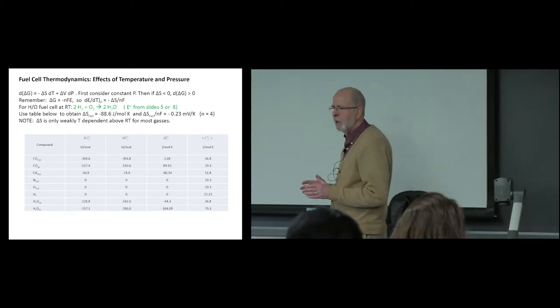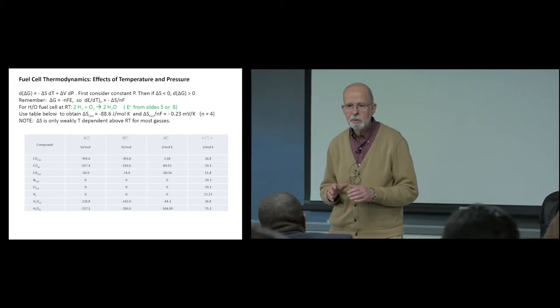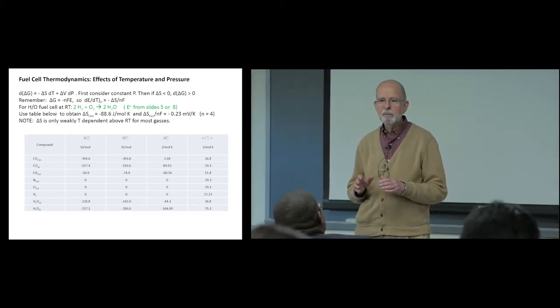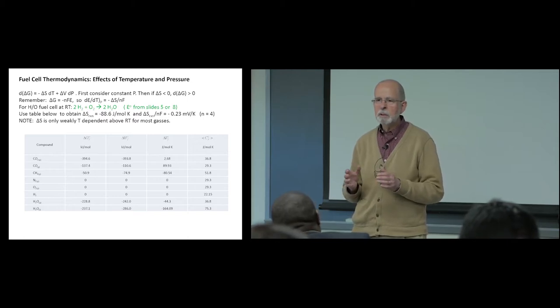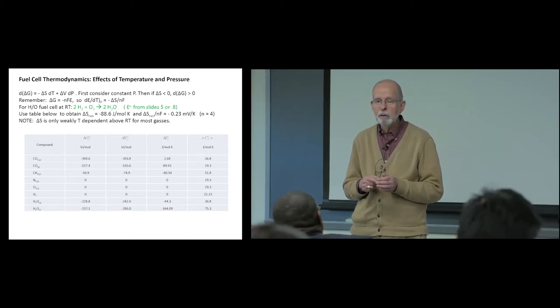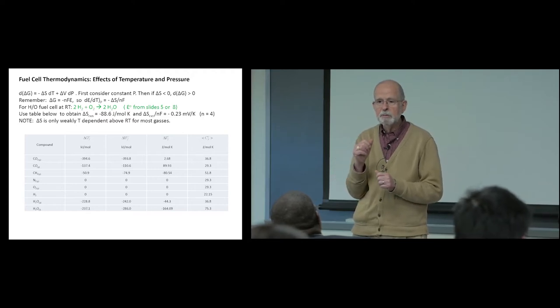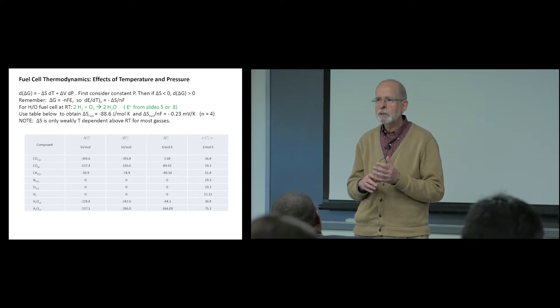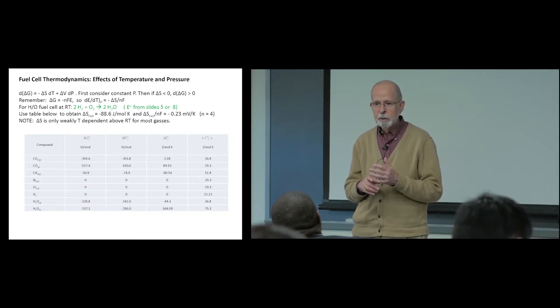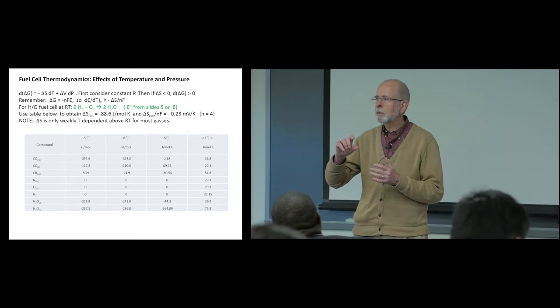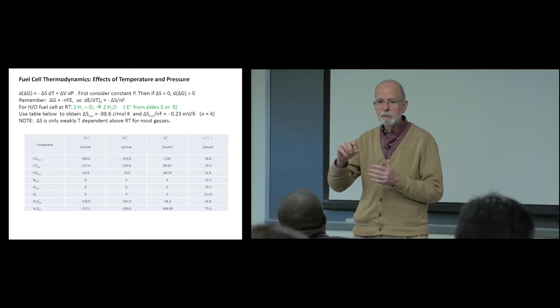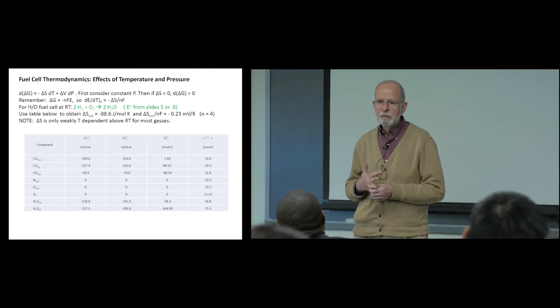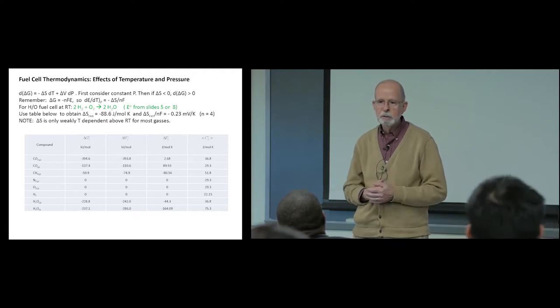In fact, the best catalyst they now have is slightly different than platinum, and it was discovered here at Cornell. It's a compound called platinum 3 cobalt. And in the fuel cell, it loses some cobalt at the surface, so it's just platinum at the surface of the nanoparticle. But the interior is platinum 3 cobalt that's got an ordered structure, and that does something very unusual to the catalyst. This is for oxygen reduction I'm talking about. The overpotential gets cut by about 70 millivolts out of 400. So that's a help. It's still not where we want to get to. But a lot of that kind of engineering and materials discovery is what's needed to go the rest of the way.